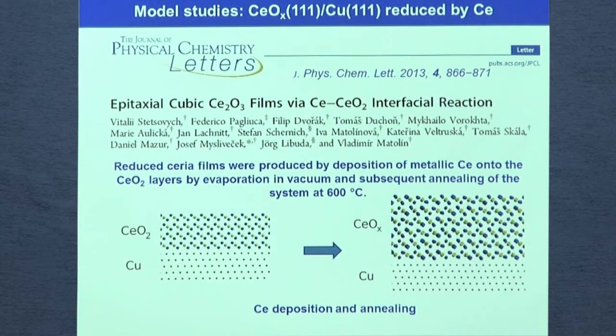In our group, we are focusing a big effort on so-called model studies. Model studies in catalysis means that instead of preparing nanoparticles, which have a lot of corners, kinks, and different planes at the surface, we can prepare atomically controlled flat surfaces where we can create well-defined structures of oxygen vacancies, steps and so on. And by checking the reactivity of these models, where we can also modelize the morphology of the surface, we can investigate, for example, which plane is more reactive than the other one, and so on.